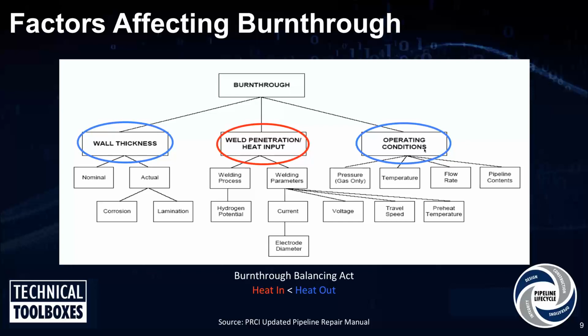So the heat that leaves the weld region leaves through the cooling aspects of the pipeline itself, which is the wall thickness, and also what is in the pipeline and how it flows. The heat going into the weld is directly affected by how the welder welds and what electrode he uses. Right? So if a welder welds hot, or at a high heat input, he's more likely to burn through than a welder that welds at a lower heat input. Now that's one thing I want to clarify too when we talk about welding heat.